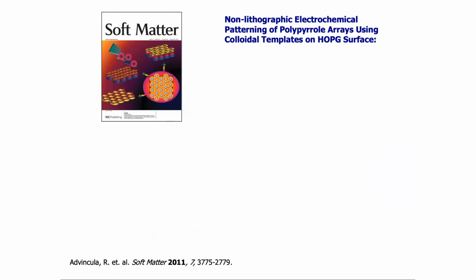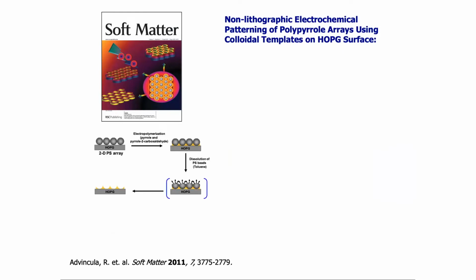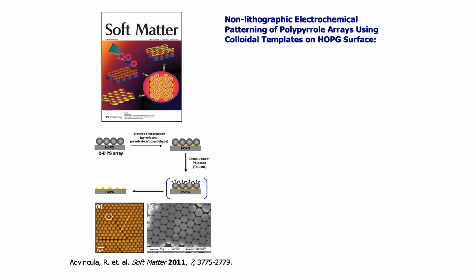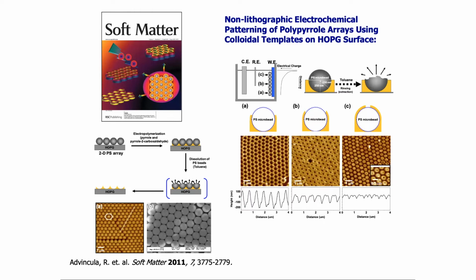So let me turn to the next patterning strategy. We use non-lithographic electrochemical patterning using colloidal templates. These templates are essentially monolayers of polystyrene that we deposit using a Langmuir-Blodgett deposition method. We will then electropolymerize through the interstitial spaces and then digest or remove the polystyrene template, resulting in an array pattern. So this is how the colloidal particles look when we first deposit. And then after electropolymerizing through it and then removing the particle template, this is what we get.